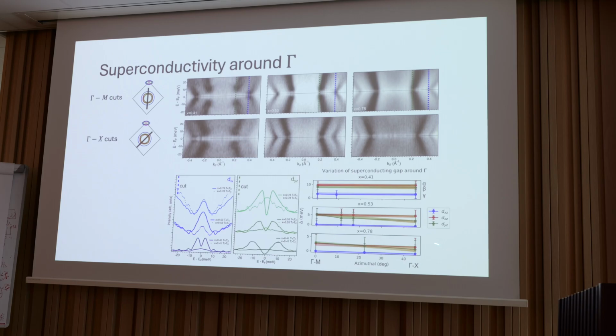And for 78%, we see that we still have this anisotropy between the 2 bands. However, if you remember, the fully potassium-doped study said that it was nodal for this beta band, which we don't see. We still resolve a gap. With that, we can maybe claim that the nodes that they see are accidental, or if they're symmetry enforced, maybe there could be some lifting of the nodes from broken time reversal symmetry. Could be one reason.